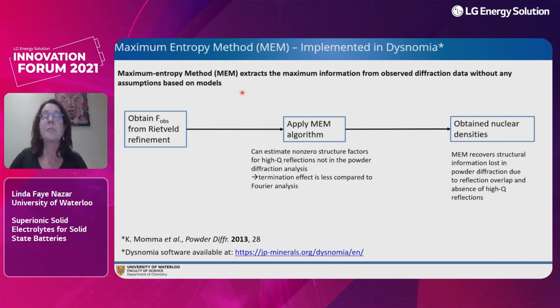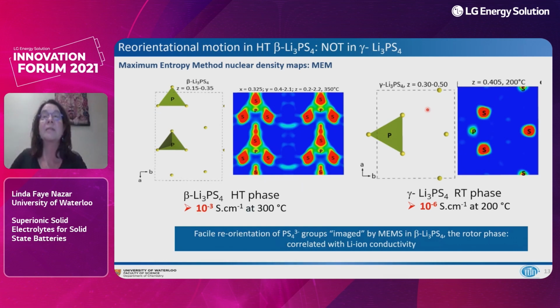So on the next slide, I'm going to show you some data from a maximum entropy method. For those of you not familiar with it, it simply extracts the information from diffraction data without any assumptions based on models. So you take your structure factors, you apply the MEM algorithm, and you can recover structural information lost in the powder diffraction data if there's reflection overlap or your reflections are out to high reciprocal space. What it does is it gives you nuclear densities, and it's really valuable for looking at lithium-ion conductors because lithium in neutrons has a negative scattering length. But here we've used it to explore the mobility of the anions in the lattice for atoms that have a positive scattering length. So you're looking here at a nuclear density map, and I've labeled the atoms in this motif, so you can see that this is the PS4 group, which is shown here in the normal crystallographic motif.